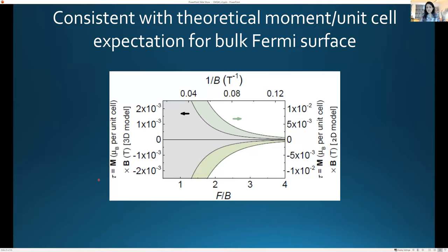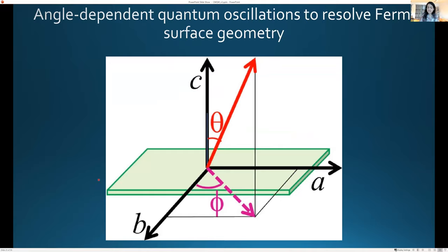The other check we do is angular rotation. And this again can tell you the geometry of the Fermi surface. So if one had a cylinder, a 2D Fermi surface, which was not isotropic, but changed from a small cross-sectional area to a cross-sectional area of infinity along the axis of the cylinder, then clearly when we rotate the magnetic field direction, the area of the Fermi surface would change dramatically.